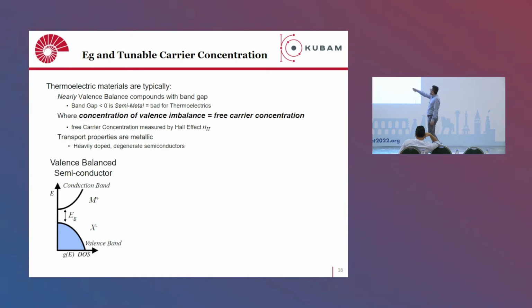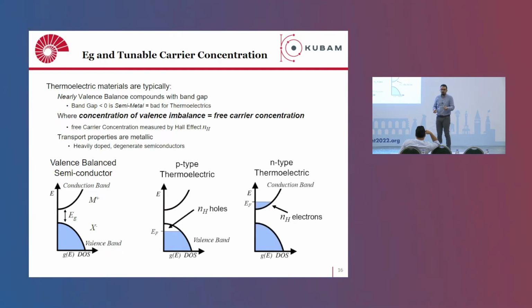So the first thing that we have to establish for the good electronic transport is the band gap. Now, material should have a band gap, because if you don't have a band gap, then you have both types of carriers. So this band gap should be small enough so that you can dope this material either p-type, as you can see here, the Fermi level in the valence band, or n-type as the Fermi level in the conduction band. But it should be also large enough, as I said, so that you don't have two separate n and p-type carriers like electrons and holes at the same time, which kills the Seebeck coefficient, basically.